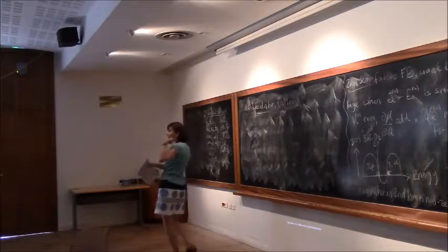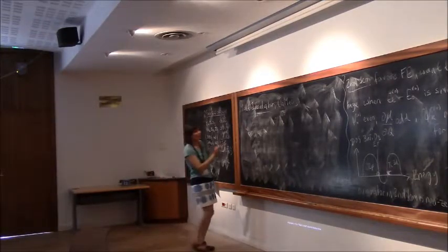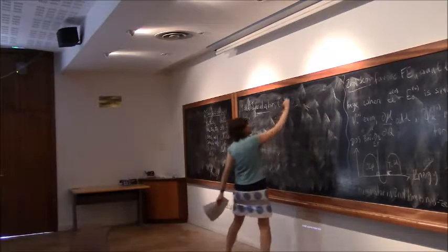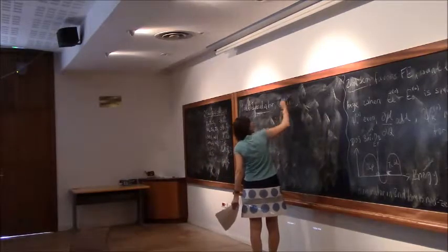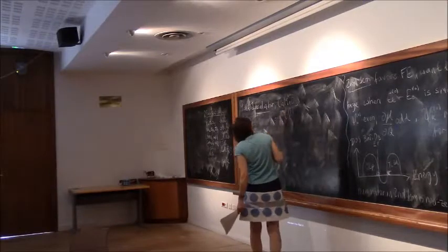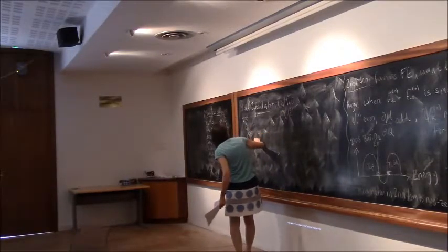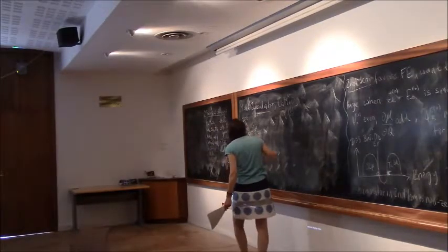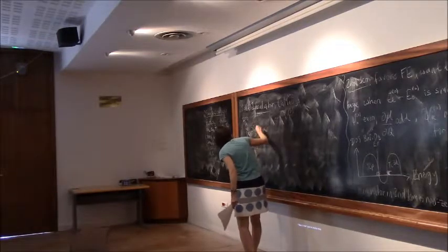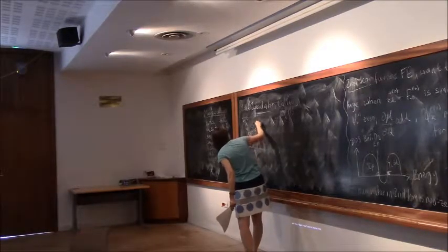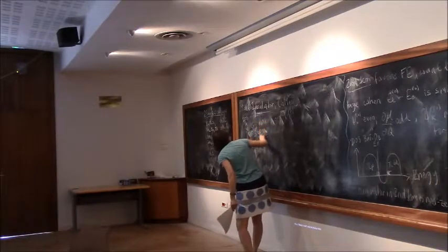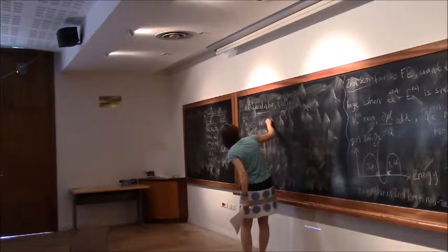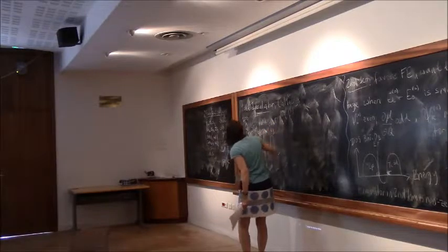Also, we can discuss that question in the context of calcium manganite. So calcium manganite is the Mott insulator. If we draw the density of states now, it's manganese 4 plus, so it's d3. There are 3 d electrons. And the band structure still has this oxygen 2p band. The oxygens are still oxygen 2 minus, but the manganese 3d t2g states sit at the Fermi energy. And then above the Fermi energy are the manganese 3d eg orbitals.